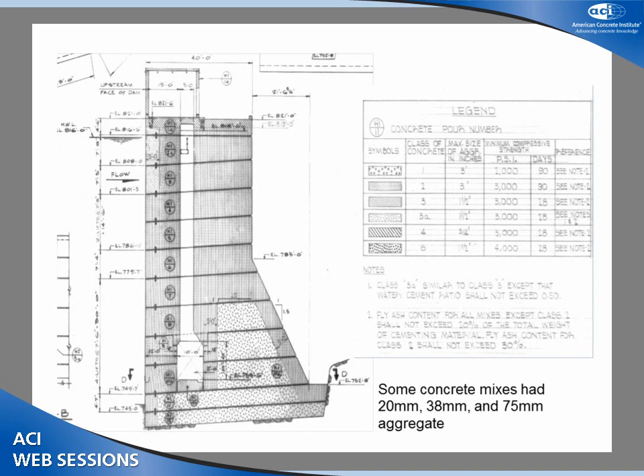And it just shows that in a dam, this is just a cross-section to where the gate structure is in the spillway section, that there are different types of concrete used there. And I know it's a difficult slide to see, but there's core concrete with up to 3-inch aggregate in it. There's other concrete with 1.5 inch aggregate. They've got face concrete on the decks where we're exposed to frost with 3/4 inch aggregate. And the highest strength there is 4,000 psi at 28 days, but most of it's like 2,000 to 3,000 psi at 28 days or 90 days even.